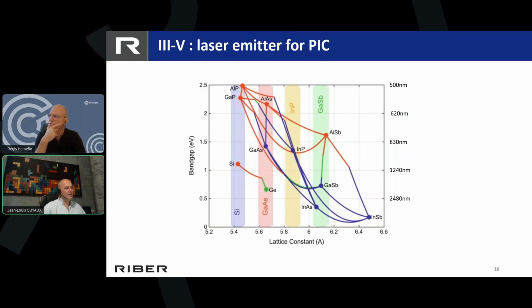Making laser emitters at the proper wavelength to have a function in, for example, the PIC industry. For the PIC industry, you see here the indium phosphide. Mixing gallium, indium, arsenic, and phosphide, you are able to reach wavelengths in the infrared, for example 1.3 micron and 1.55 micron emitters. Why those two wavelengths? This is because this is the low loss window you have in optical fibers. Of course, these are 3-5 semiconductors, thus they need to be grown on indium phosphide. They cannot be grown yet on silicon.